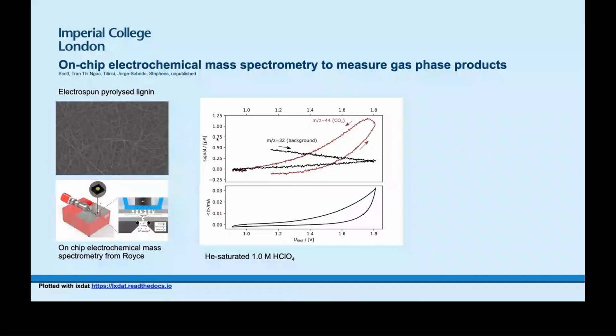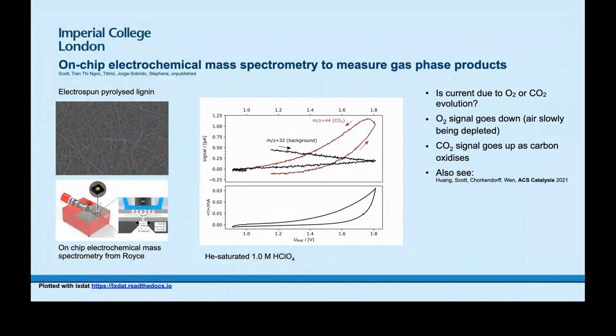And what we found is actually here, so this is a signal at the mass spec. What we found is that the signal for oxygen actually goes down, but what we have instead is a signal for CO2 going up. So this is essentially the carbon corrosion. We're making CO2 in the gas phase, and we're not actually producing any oxygen, because as I said, we're actually seeing a decrease in the oxygen background.